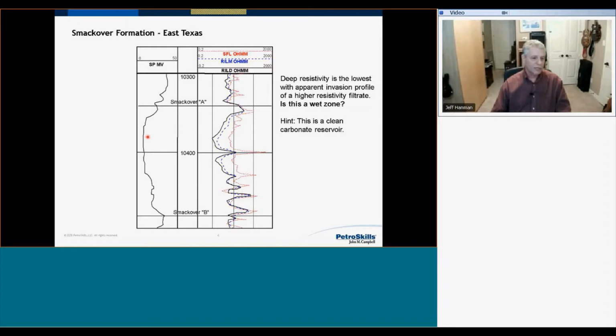What we know from the SP, for those of you who may know about SPs, but many of the people who've only dealt with oil-based mud may not have seen an SP. This SP tells us, for example, the well was drilled with water-based mud, and the mud filtrate has a lower salinity or is more resistive than the formation water. And this invasion profile shows increasing resistivity with decreasing volume of investigation into the formation.